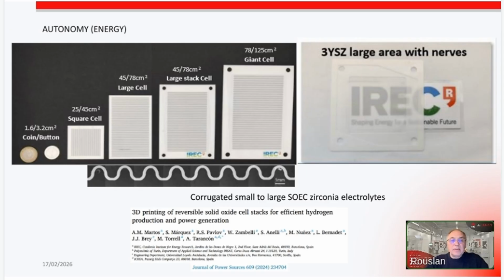Here again, what additive manufacturing brings as an advantage: you can see this corrugated structure under the main picture, and this corrugated structure, versus flat solid electrolyte cells manufactured by tape casting, gives more efficiency, not only in terms of the production of hydrogen, but also much better mechanical resistance to the cell, because the biggest issue with the flat cells is reliability and the capability to work under pressure to produce hydrogen. Here we could solve this challenge using 3D printing. So it's really about the advantage that additive manufacturing can bring. You cannot do this by tape casting.